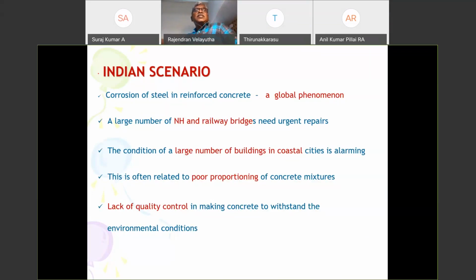Poor detailing and concrete mix design is taking place. As Anil was saying, it is information for me that Ramco has an exclusive product for infra where you have very high slump retention. People try to save a little money on admixtures. They don't choose the right admixture, so they get into a problem of slump retention, they don't get the slump and they are not able to pump the concrete. As they are not able to pump the concrete, the tendency at site is to add water. Once they add water, the water cement ratio increases, and once the water cement ratio increases, compressive strength is reduced, resulting in a lot of issues.